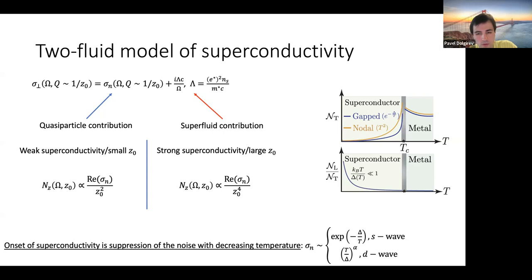What I want to now point out is that without even doing calculations, if I could have guessed this form, I can already give you answers because I know that normal conductivity in the superconductor case, like in S-wave superconductor, will be exponentially suppressed. And in reality, dramatic suppression of noise is a signature of superconducting to normal metal transition. And if this was a D-wave superconductor, then there is still suppression, but maybe not that dramatic, say, power law as a function of temperature.